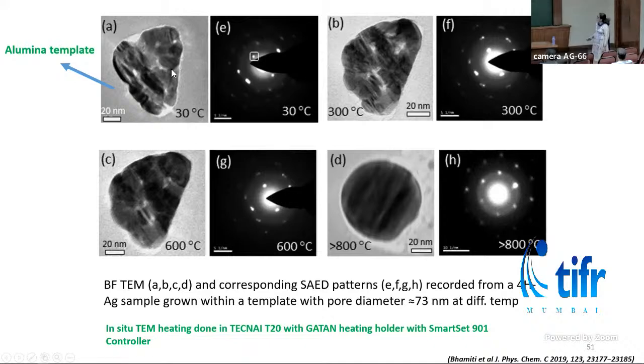This is the diffraction pattern of the wire at room temperature, which tells that this wire is 4H in phase. When we heated this sample in TEM at 800 degrees centigrade, we could see that this bamboo-like morphology has disappeared completely and the sample has transformed to a 3C material. When this diffraction pattern was indexed, it was found to be the 111 plane of 3C.